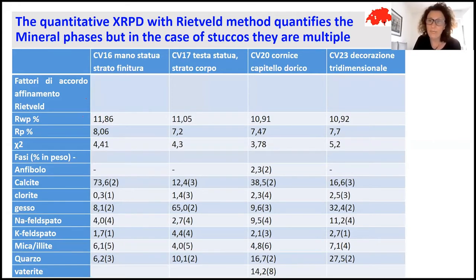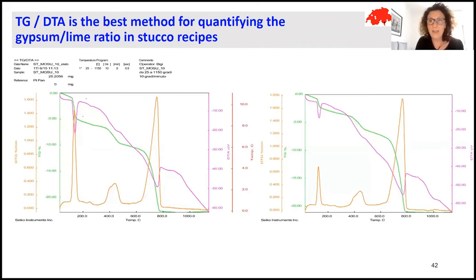But we should say that the mortar and the stucco are composite materials with many mineral phases, because they have sands with different mineral components. So this quantification is not always straightforward. I think the best method for the quantification of the ratio of lime to gypsum is thermogravimetric analysis, which uses the heating of the sample while observing the loss in weight at different temperatures.